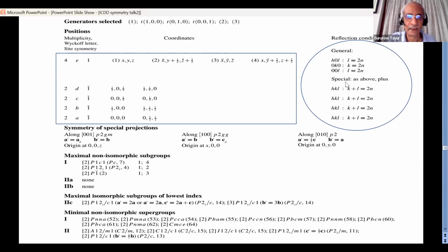That means in the list of hkl reflections which you have, the projection reflections h0l will appear, and also the 0k0, which are the axial reflections. The value of k will now be 2, 4, 6, 8, and so on. Only those will appear. And in the case of h0l, only the even values of l will appear, indicating the presence of the c glide and indicating the presence of the 2-1 screw axis.